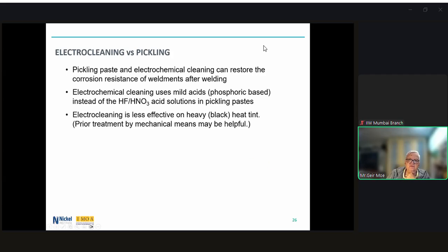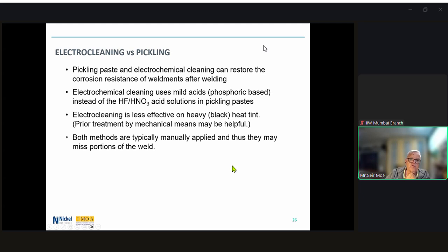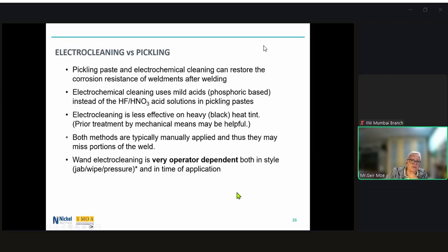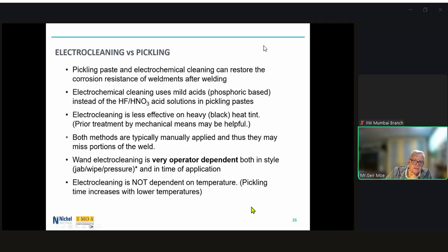Electrocleaning is less effective on heavy black heat tint. Prior treatment by mechanical means such as abrasive blasting or grinding may be helpful. Both methods are typically manually applied, and thus they may miss portions of the weld. Wand electrocleaning is very operator dependent, both in style and in time of application. But electrocleaning is not dependent on temperature.